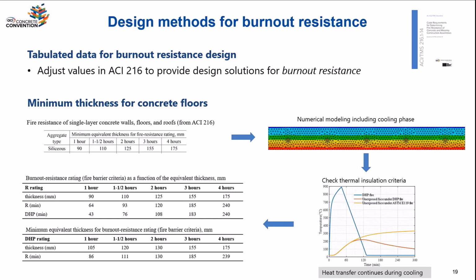So we can model those floors in a finite element model. Now we have the material properties owing to the experimental task that I've shown. And we can look at how the temperature on the unexposed face continues to increase for a while during the cooling phase, and then eventually cools down. And so by repeating these analyses for different thickness of the floor, we can find the minimum thickness such that this maximum does not exceed a limiting temperature.